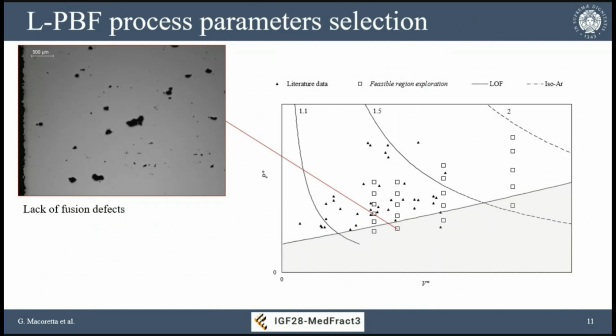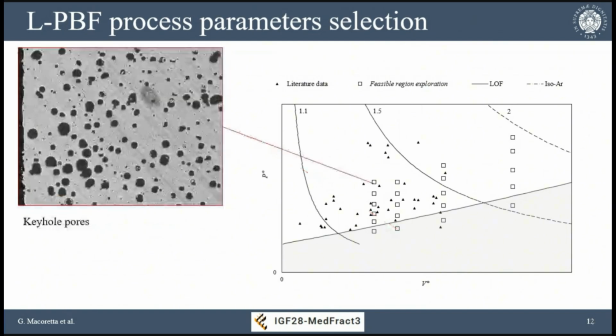Let's go through the first experimental evidence. We can see that points belonging to a region below the lack of fusion boundary feature the standard defects that occur with lack of fusion—not huge lack of fusion, but sporadic lack of fusion phenomena, as predicted by the model.